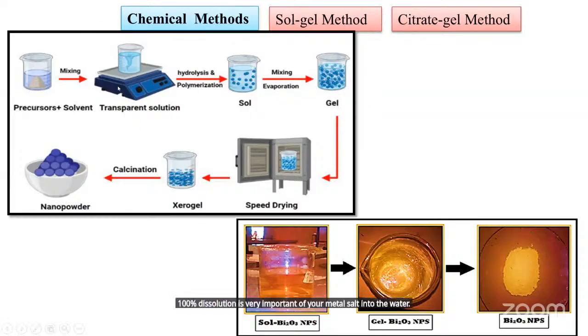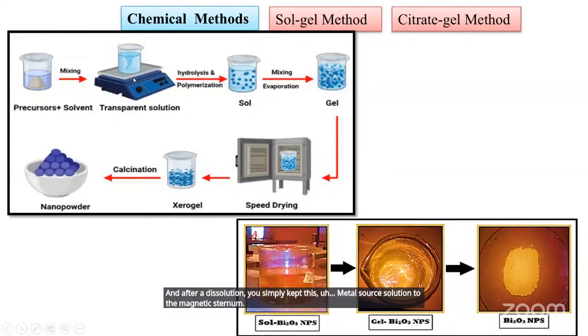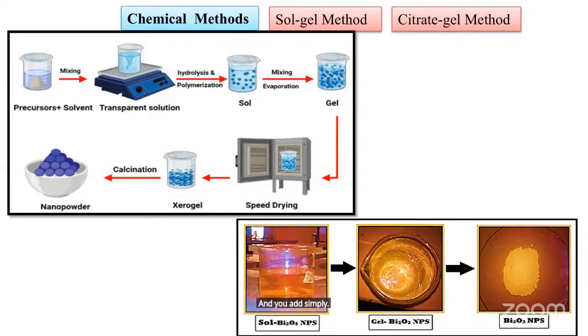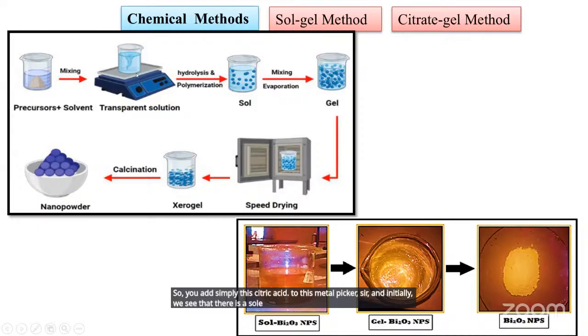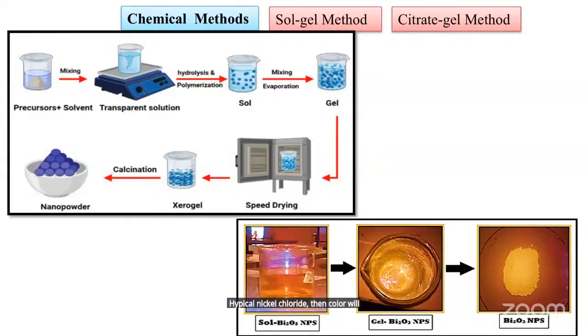And after dissolution, you simply keep this metal salt solution on the magnetic stirrer and you add simply the citric acid solution of desired concentration. That may be 0.01 mole or 0.1 mole, or whatever your concentration is, whatever your stoichiometry is. So you add simply this citric acid to this metal precursor, and initially you see that there is a sol. Means initially when the citric acid is not added, the color of your material is different. If it is nickel chloride, then the color will appear green. Copper chloride may have a blue color, or any other transparent color will be there.